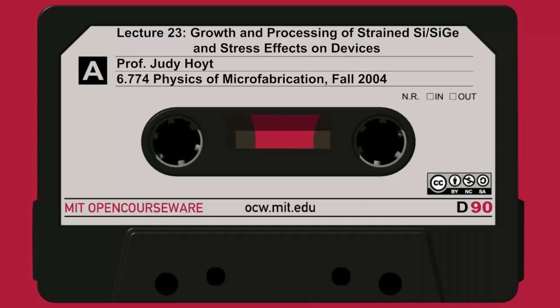So if you make a FET and you make this as your channel, the electrons want to go into the strained silicon. The holes want to be on the silicon germanium side. So this is what's called a type 2 band alignment. So you can make lots of interesting devices just by taking silicon and straining it on relaxed silicon germanium.